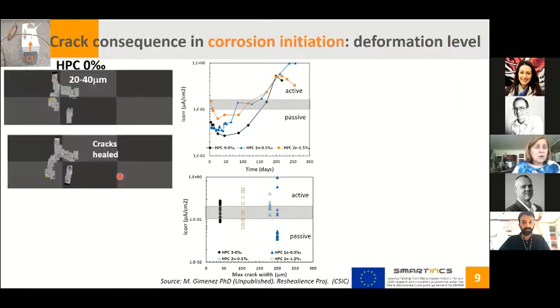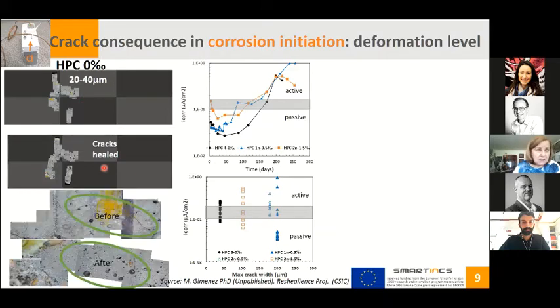easier and sooner. If we compare this corrosion rate with the crack size, we observe that the corrosion initiation has occurred in all the cases with this concrete. What happens in reality? We can have small cracks. This crack can be healed, as observed here. However, the corrosion has been initiated, so it is not enough to support and protect the reinforcement.